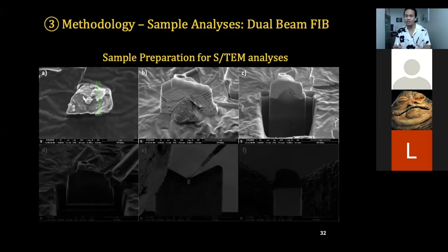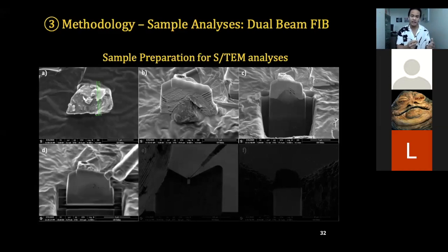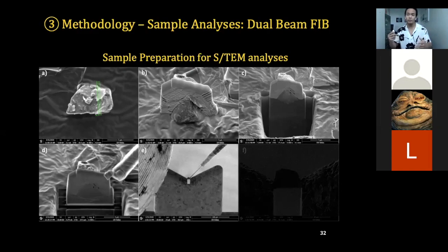Once we've done that, we insert a micro manipulator needle near our sample, which is shown on image D. And then we weld that needle onto our sample using platinum. Once it's been welded, the underside of our sample is then cut off and cut free from the substrate, and this needle is then pulled out. Image E shows our needle being inserted onto a copper grid, which will go into the next instrument.